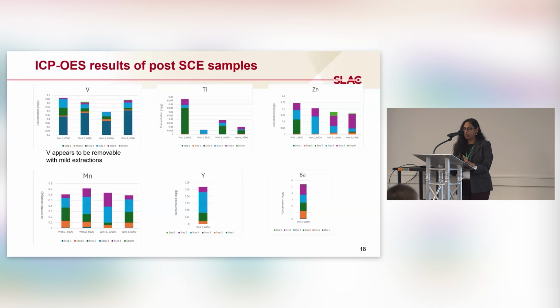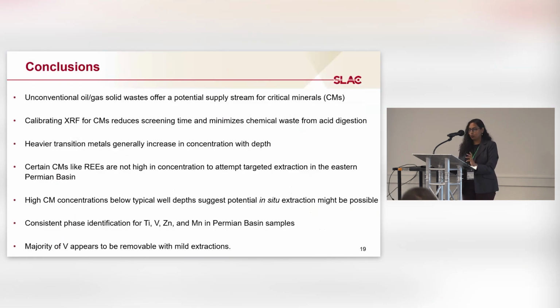Concluding the talk, unconventional oil and gas wastes offer a potential supply stream for critical minerals, at least for the elements that we were able to find. Calibrating the XRF for these critical minerals reduces the screening time and minimizes the chemical waste that would be produced with acid digestion if we had to do it for all samples. Heavier transition metals were generally seen to increase with depth. Even though we wanted to see rare earth elements in our samples, we did not really see much. So the Permian Basin, at least the area that we got our samples from, looks like it's not a great spot to find rare earth elements.